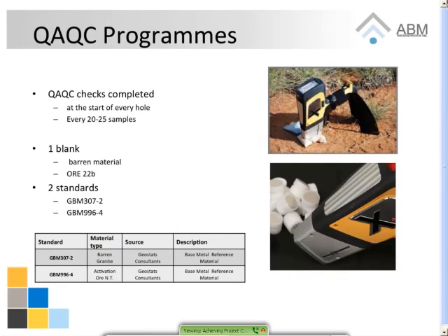ABM undertakes check samples at the start of every hole and about every 20 to 25 XRF readings taken. They use two geostat standards and also blanks to ensure there's been no cross-contamination on the front window of the instrument.